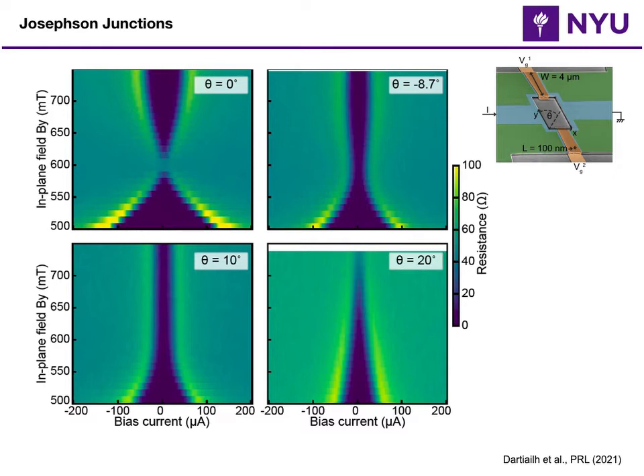So if I tilt the in-plane field away from this ideal By direction, this gap closing should change. And indeed, as we change this theta value from this ideal angle, you can see on the top left there is a very clear gap closing and opening. As we get to about 20 degrees, that whole transition completely disappears.